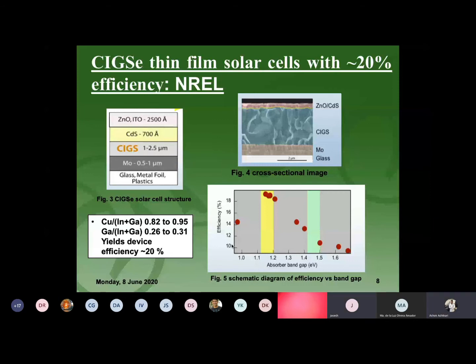They also found efficiency around 20% observed with copper content between 0.82 to 0.95, and gallium content 0.26 to 0.31. This is the example I am focusing on to make our absorber layer.